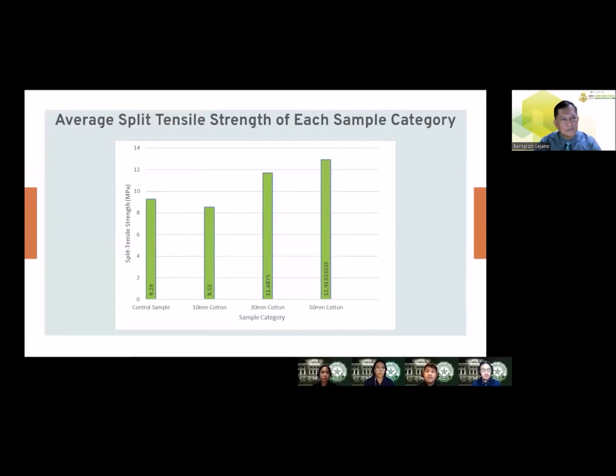It is to be noted that the 10 mm fibers do not benefit the split tensile strength of concrete, while longer fiber lengths prove to have an adequate increase of split tensile strength, with 50 mm being the highest.